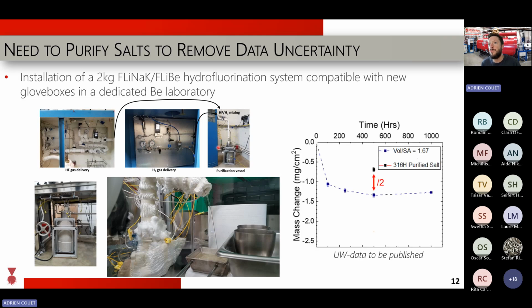So that's how you retrieve your salt from the purification vessel in a glove box. And why I say it's so: we have more data now on this, and we have a paper in preparation to show this kind of effect of purification on corrosion kinetics. But 316 stainless steel, approximately a factor of 2 lower weight loss when you're working in a purified salt, right? So really, purification of salt is very, very important.